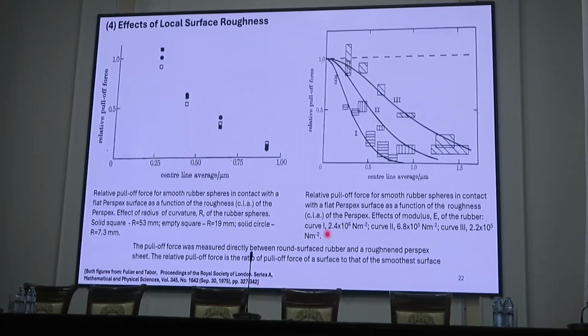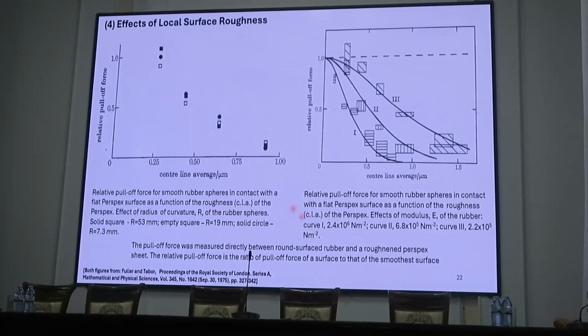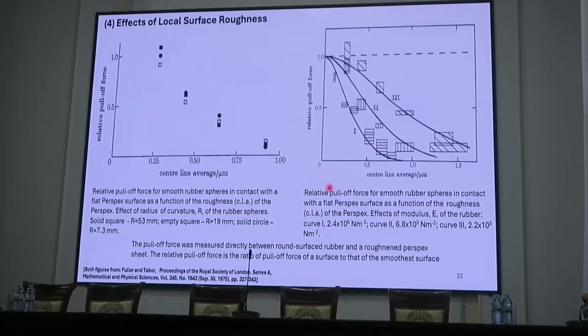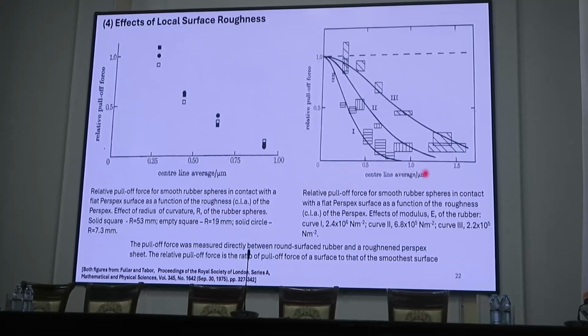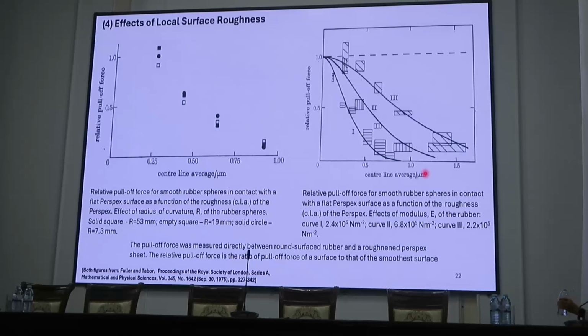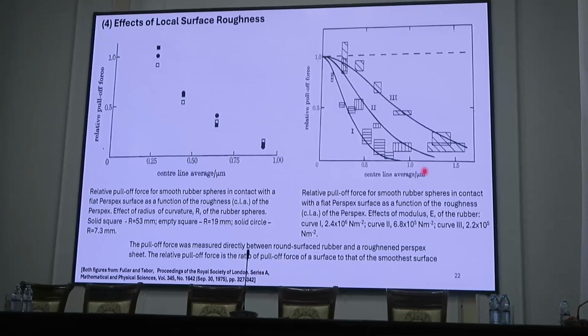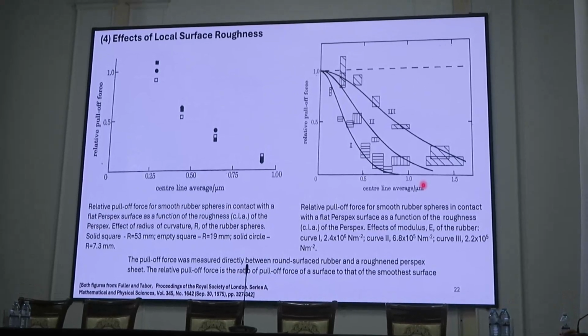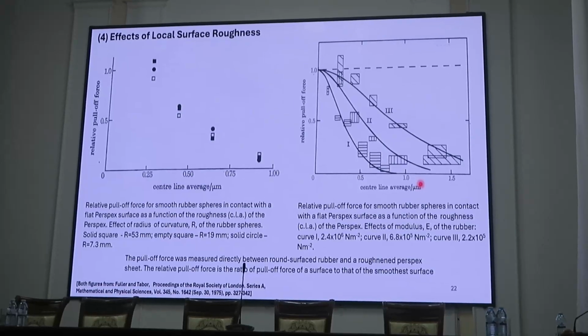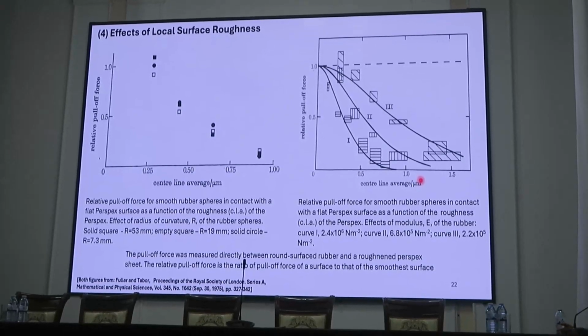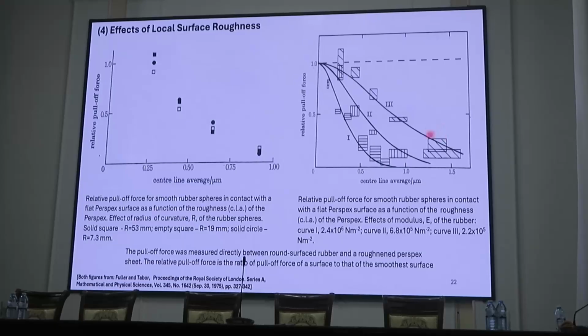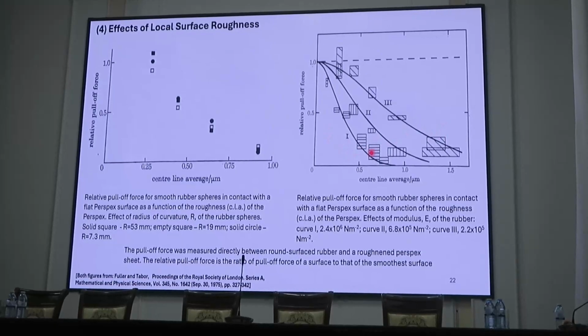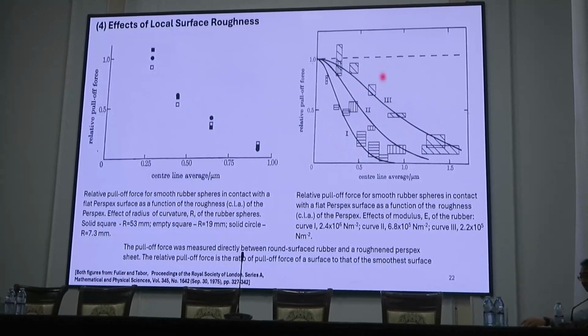Another factor is surface roughness, and we are quite aware of the surface roughness issue. As you increase the surface roughness, the pull-off force will go down, that means adhesion is less. That's why nowadays some people are trying texturing on the implant so that we can reduce the adhesion force. The pull-off force also depends on the modulus of the material.